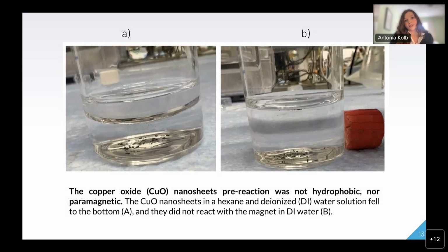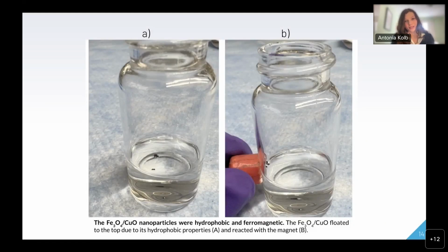Therefore, I used dodecylphosphonic acid and dibenzyl ether as protective coatings to make the copper oxide nanosheets hydrophobic, and the magnetite nanoparticles allowed for the powder to become magnetic. The magnetite and copper oxide powder from the incipient wetness reaction and the solvothermal reaction displayed both hydrophobic and ferromagnetic properties. First, I placed a few particles of the magnetite and the copper oxide into deionized water. The powder remained above the surface of the water, demonstrating its hydrophobicity, and it also reacted to the magnet seen here.